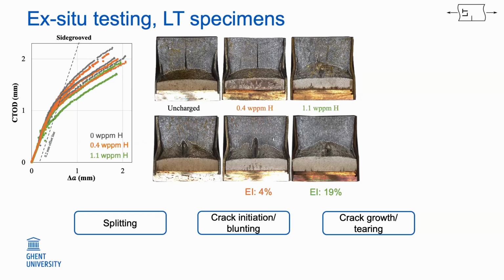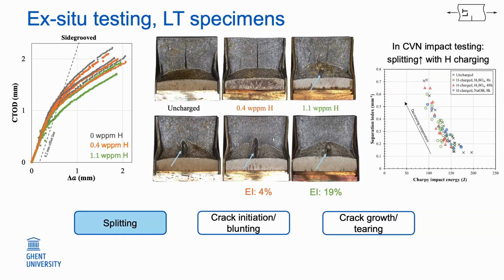For splitting, you can already see, because this is LT, the splits will be going along the crack extension. So we'll actually be splitting the crack front in two. And here we could not really find a trend except for the higher hydrogen concentration where really every specimen was split. But for the lower hydrogen concentration, this was not really observed. But we also did Charpy testing where we could see a really clear trend where if you charge with hydrogen, and then at the higher temperatures, the Charpy test did have more splitting in LT.